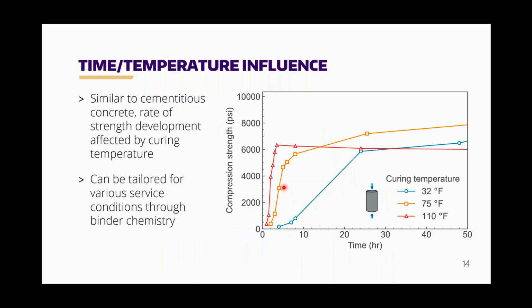Also similar to cementitious concrete, the rate of strength development is affected by curing temperature. And so what I'm showing you here is the compressive strength versus time for cylinders that were cured and tested at 3 different temperatures, at 32 degrees Fahrenheit all the way up to 110. And what you see is that as the curing temperature increases, the rate of strength development becomes quite rapid. You get 100% of the strength in about 2 hours. And then it levels off here at a lower strength than, of course, the colder temperature values. As you cure at a lower temperature, the rate of strength development goes from about 2 hours to maybe 2 days.